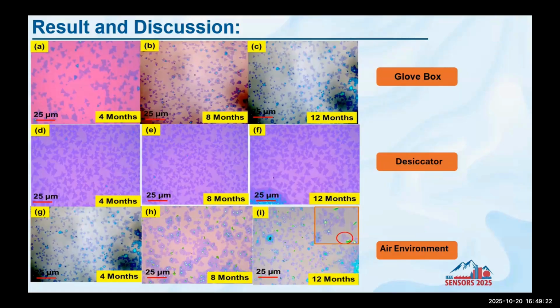At the end of each month, I took optical images and tried to find defects. As you can see, for the samples kept in the glove box and desiccator, we didn't find any defects or degradation on the MoS2 surface. But for the samples kept in the air environment, which is the lab environment at normal humidity, after more than 8 months we found a lot of cracks on the surface, starting from the nucleus at the center of the triangle. We found a lot of cracks on each triangle. So this study we have done.